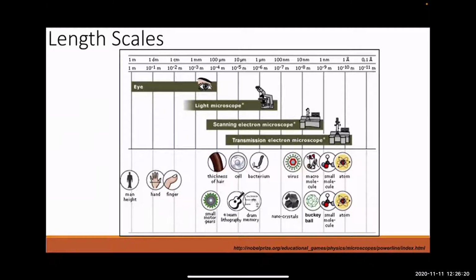And then the TEM, especially with what are called aberration corrected TEMs, which is a fancy term for correcting a lens defect, an aberration. They can now get down to incredible resolutions measured on the order of tens to hundreds of picometers. So fully into the length scale of an atom, so atomic resolution.